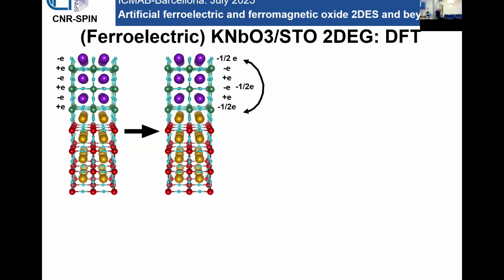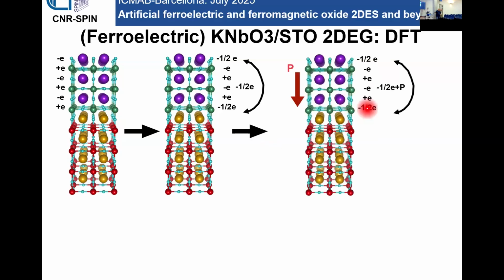Then if we add the ferroelectricity on top of that, if the system is ferroelectric, we have another degree of freedom. The polarization, of course, will add up to the charge which is transferred to the interface. So if the polarization is up or down, you can favor or disfavor the formation of 2DEG. In particular, if it's down, there is an increase of charge carriers transferred, electrons at the interface. If it's up, on the other hand, there is a decrease of this charge density. So these are very simple, let's say,